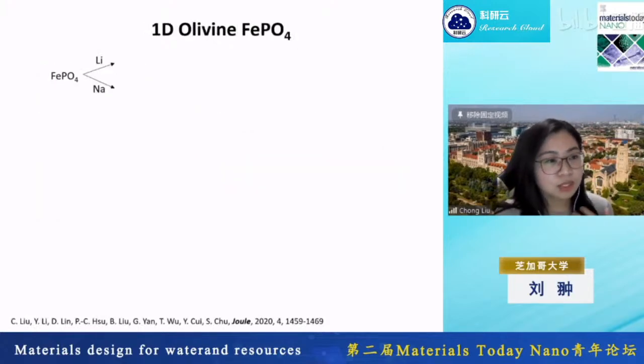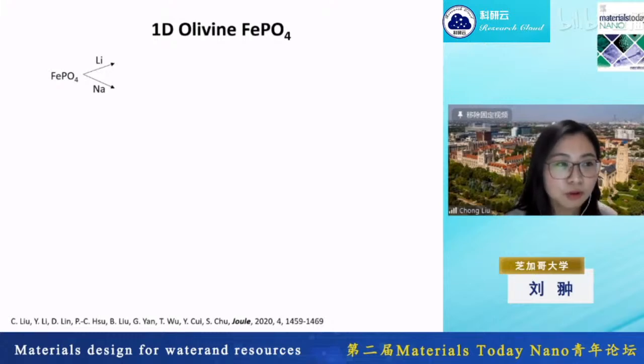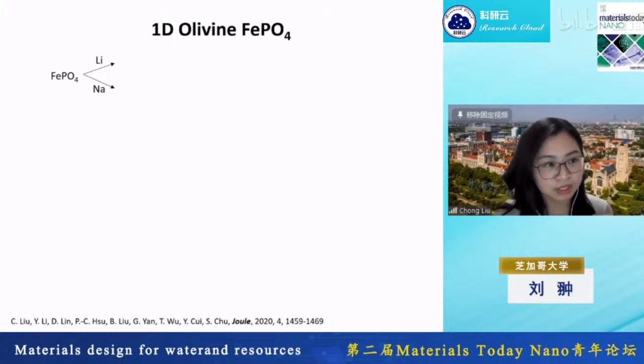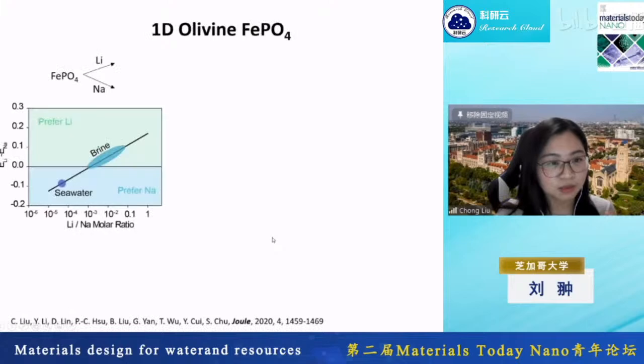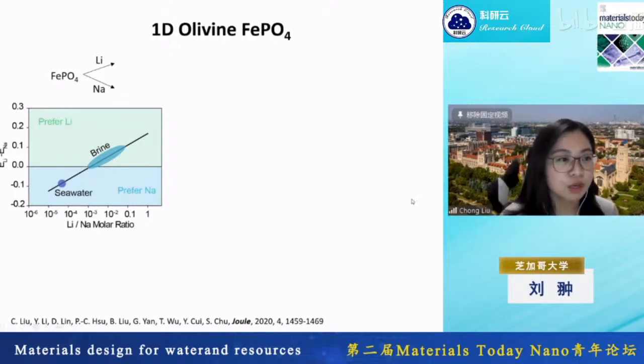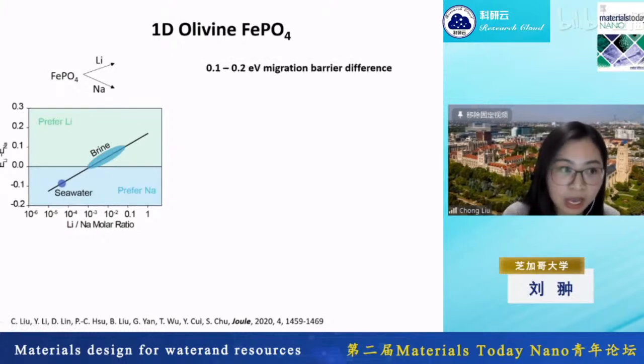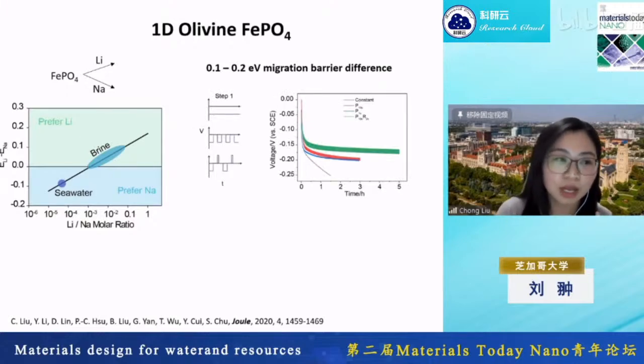So the first work we did actually follows pretty well the trend predicted by the intercalation voltage, because we do see that if you look at the lithium iron phosphate intercalation potential, it can tolerate 3 or barely 4 orders of magnitude difference in their concentration. And as well, you have an added benefit of the migration energy barrier difference. And so intrinsically, this material has a good selectivity to lithium.